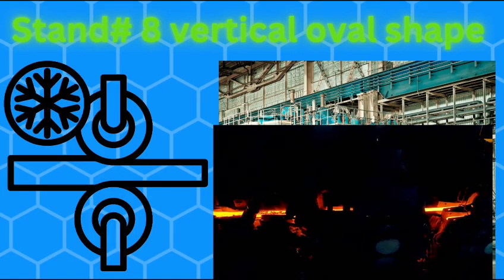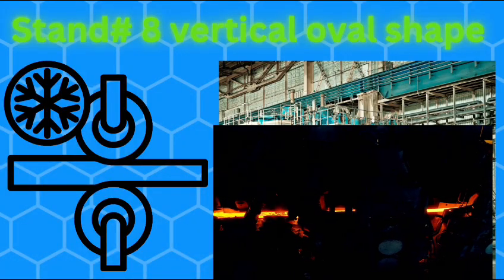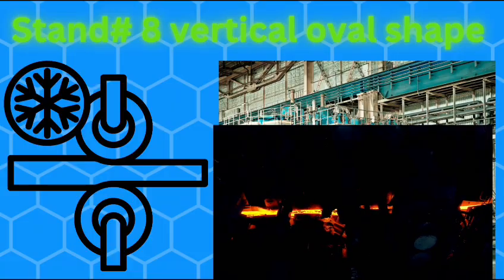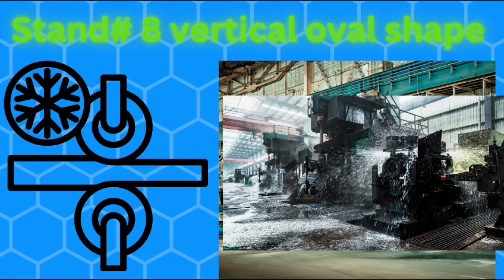Stand number 8 is a vertical stand with two vertical rollers; both the rollers rotate in opposite directions. The hot billet passes through the center of the groove rollers. Because of the rotation, the rollers grip and pull the billet in the forward direction. The reduction size is 34 mm to 26 mm. The reduction size is 8 mm. In the vertical stands, force is applied by the sides only. This converts it to round shaping for finishing of the billet.